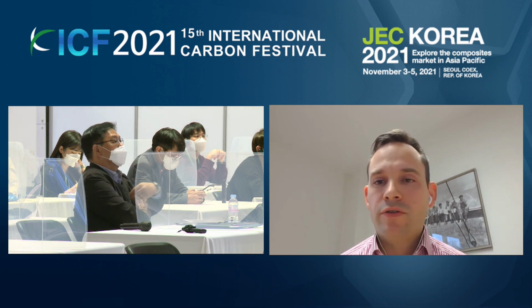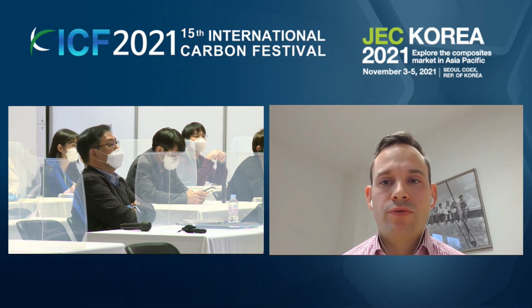Yes, we do. We have already made a lot of different tapes for injection molding processes. So the thickness is a very important property. If it's too thin, you have issues with the shrinkage of the original material, and you get cracks inside the tape. And if the tape is too thick, you have issues with a good impregnation of the material. So the thickness is a very important point to have a good adhesion and to have no cracks inside the material.